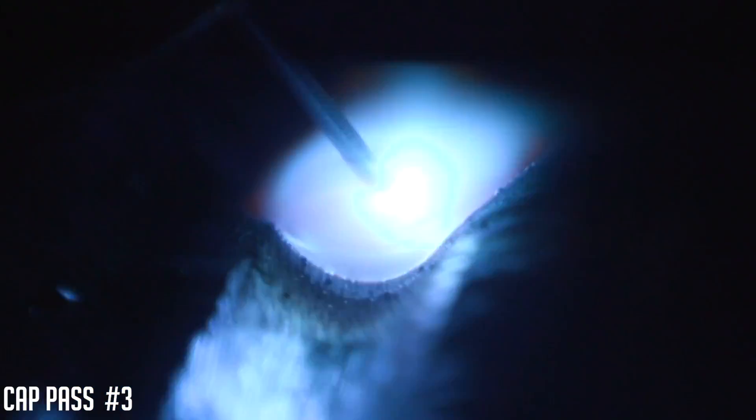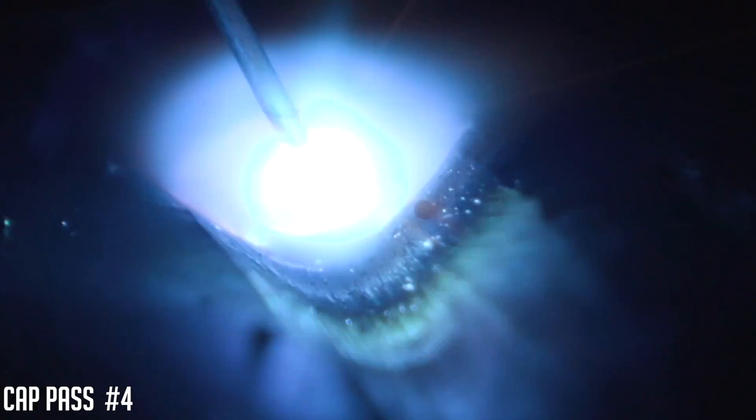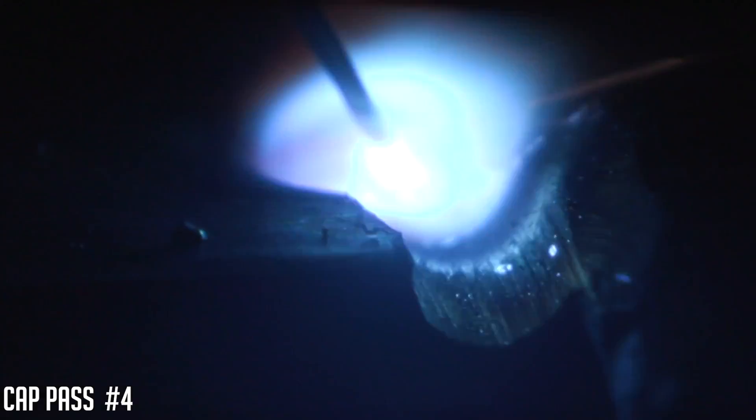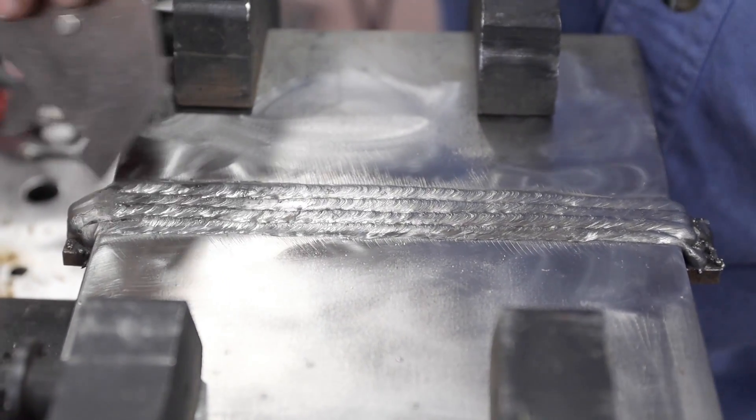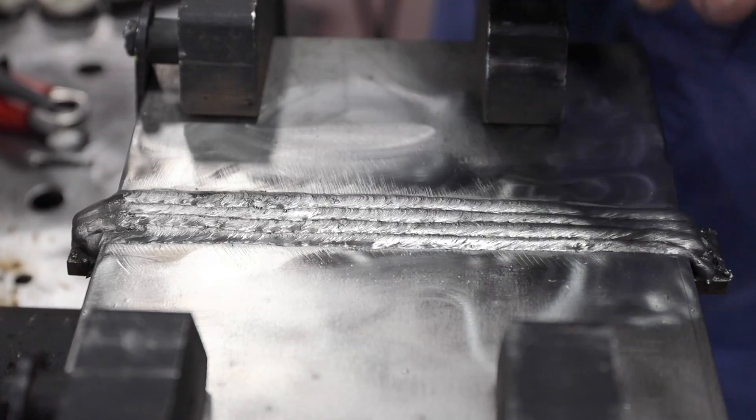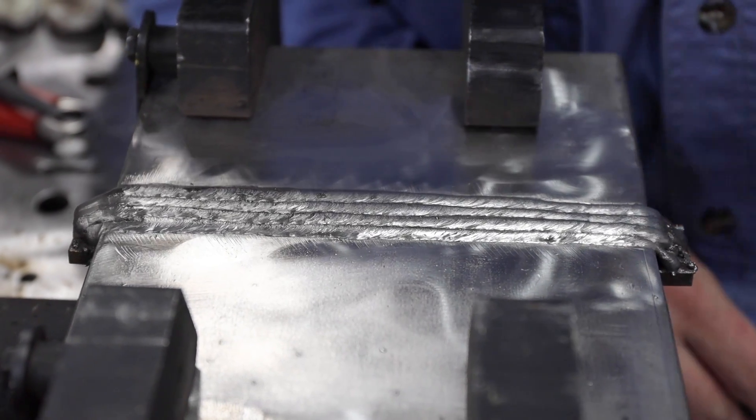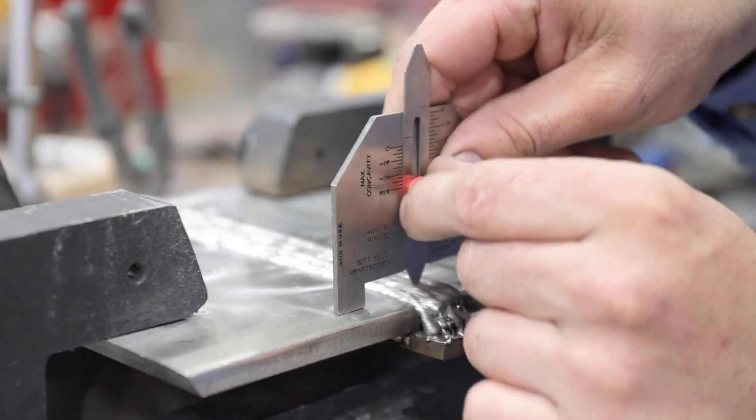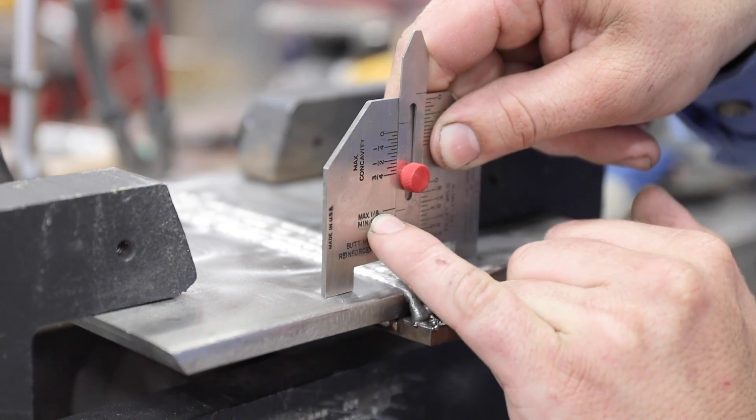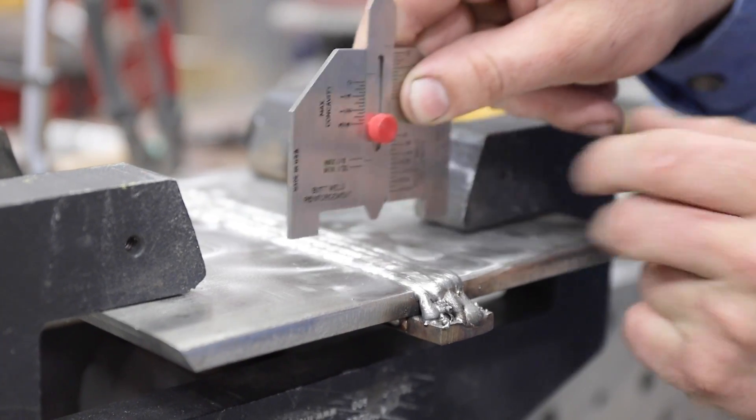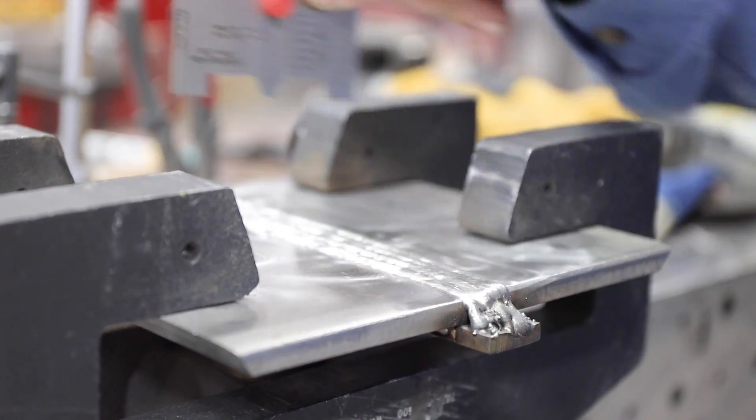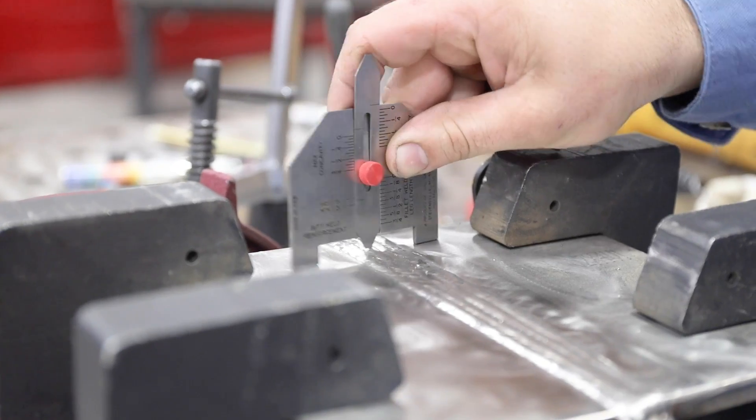We got this all done. I'm pretty happy with it. I mean, it came out pretty all right. We're nice and straight right here. A little convex right here, but I don't think that's over an eighth inch. I think we're right under there. We got good tie-ins here. That's what we're looking at. No undercut or underfill. We even got a fill right here. This is where usually the problems are in the test, is right here when you stop. That's why I kind of alternate my beads. I run this way on one, then run this way when you can on a flat test or horizontal. So we're going to check random spots here. This looks like the highest spot. So go right here. So here's 1/32nd. Here's 1/8th. It's right there below 1/8th. It's always good to check a couple spots here. Go right here. I'm not even going to lift this off. So we're on 1/8th. Let's go down the other end. It's almost the same as this, but a little bit less. So I think we're good. We're all good.